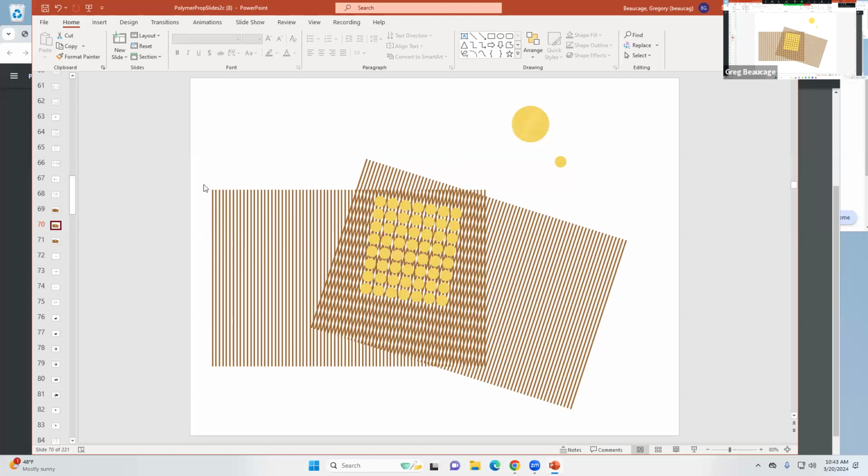Or you could come in with multiple wavelengths. You just don't monochromate your beam, and then you get kind of a starry night pattern called a Laue pattern. Some of the wavelengths will give rise to fringe patterns that are in the right position to give you the diffraction peak. So that's another way to do it. There are three ways to get diffraction to work for crystals. For polymers, it's not a problem because they're just gooey things all over the place, so it doesn't matter. Some of them will meet this Bragg condition. Anyway, that's kind of the operation.